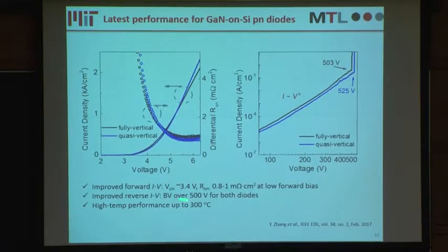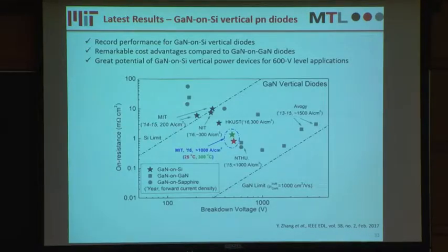And also, if we look at the reverse characteristics, the breakdown voltage increased from 200 to 300, to over 500 in our latest result. These devices can also have high temperature performance up to 300 degrees C. And if we look at the performance in this figure of merit, this is our first demonstration three years ago, and this is our latest result. So it's already a remarkable improvement from here to here.